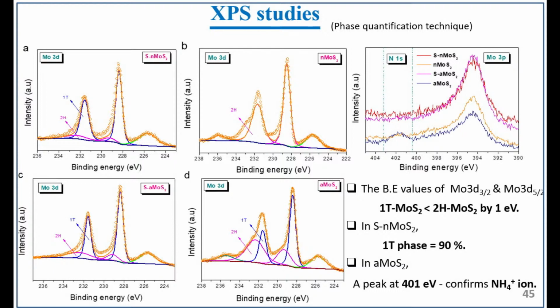In the XPS studies, we can do the quantification of both phases, because the binding energies of the Mo 3d5/2 peaks are about one electron volt apart. You can see that 1T has a lower binding energy than 2H, because the metallic form has a lower binding energy. So from the peak areas under the peaks, we can quantify how much 2H and how much 1T you have. Wherever you are using sodium molybdate with SBA-15, you have an enriched 1T phase, and wherever you are not using SBA-15, you have the 2H phase as dominant. So there is a difference in their MoS2. Similarly, in the case of the ammonium precursor, we have a nitrogen 1s peak around 401 eV, so we are able to detect trapped ammonium ions in the case of ammonium molybdate.